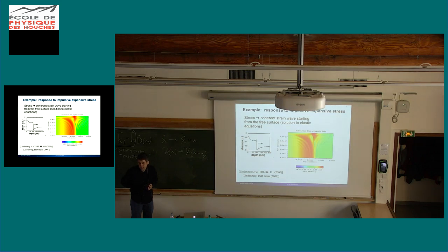But in fact, to see these oscillations in X-rays, you need a substrate that heterodynes the response of the crystal. You won't see the result of Aaron Lindenberg's thesis if you were looking at a thin film. I think it's very important to reference not a reflection from a surface, but a reflection from a bulk. You mean if you had a freestanding thin film? Even if the substrate is simply reflecting at a different Bragg angle, you don't have an interference of the Bragg reflection of the substrate. But you still have the outer surface.